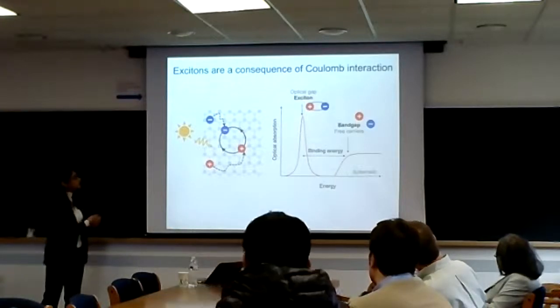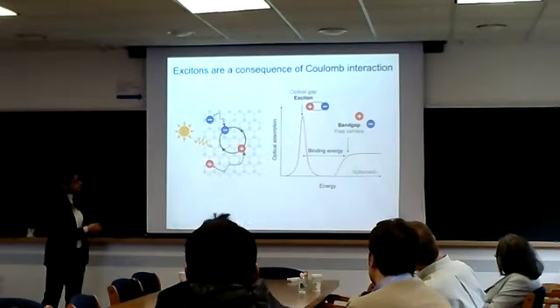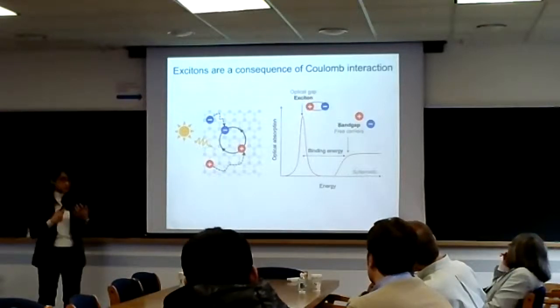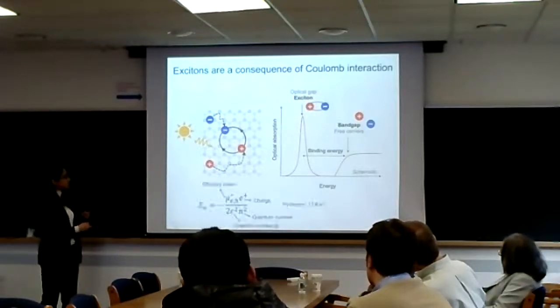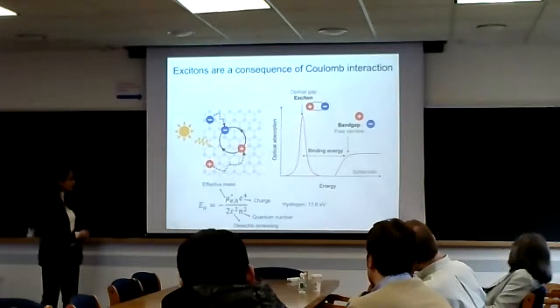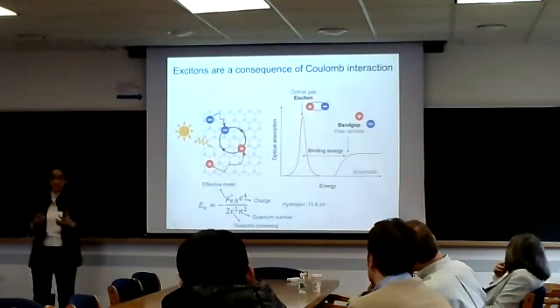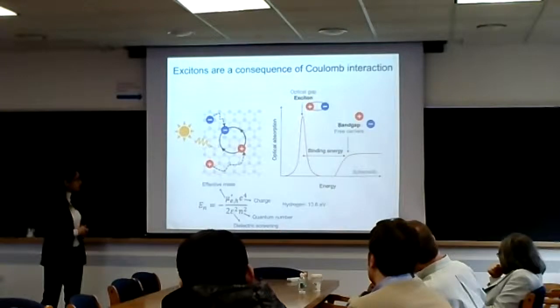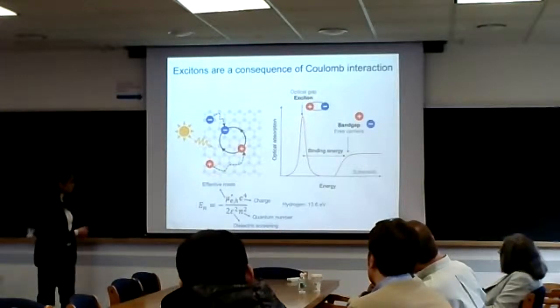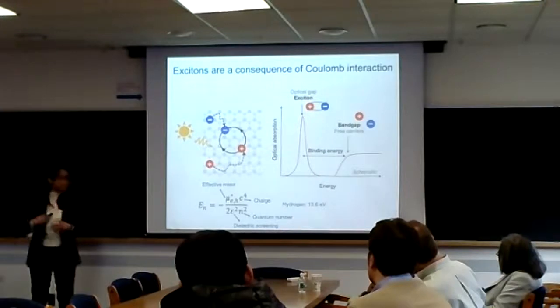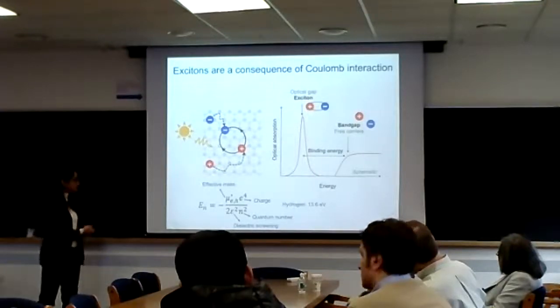It's called the exciton, and it's stabilized with respect to this band edge by the so-called binding energy. If we were to calculate the numbers for the binding energy, in the hydrogen case the familiar number is 13.6 eV, which we learned in high school. The ingredients that go into this are the effective mass, the dielectric screening, the state number, and the charge.